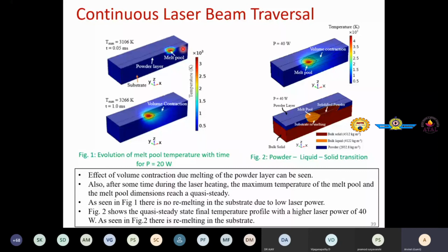The melt pool is shown by a boundary, and locally you can see the heat is consolidated at the current location of the laser. Then as the laser moves, the previous track gets solidified, and then there is interaction of the current melt pool with the forward powder particles. Such information can be very useful because you can understand the role of thermal fluid phenomena, and its role on further microstructure formation or melt pool dynamics, or some defect formation like balling or porosity. All these can be understood using such modeling technique.